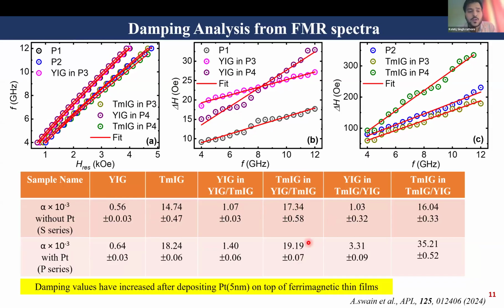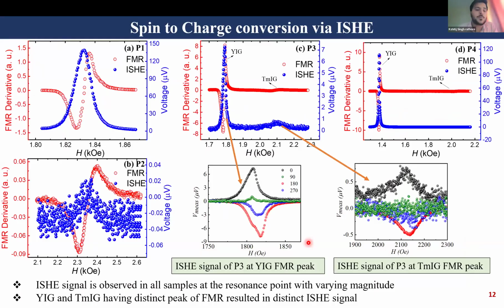So for this, we did the measurement for the inverse spin Hall effect simultaneously while the FMR was taking place. That is shown in this red curve, and the blue curve signifies the signal from the nanovoltmeter, that is, a voltage signal of the corresponding samples. And clearly here, the bilayer sample of YIG and TMIG has two distinguished peaks. Corresponding to them, there is a blue curve of the ISHE signal. These ISHE signals, when rotated by 90 degrees, showed opposite sign behavior, which clearly signifies the presence of spin pumping.